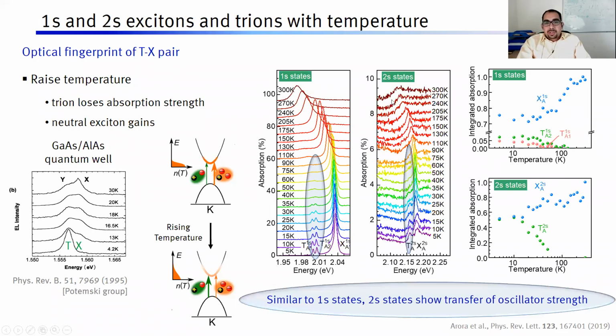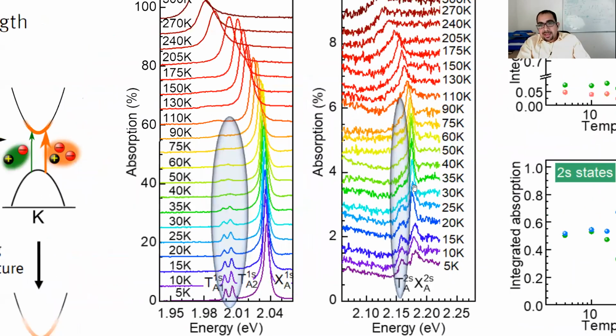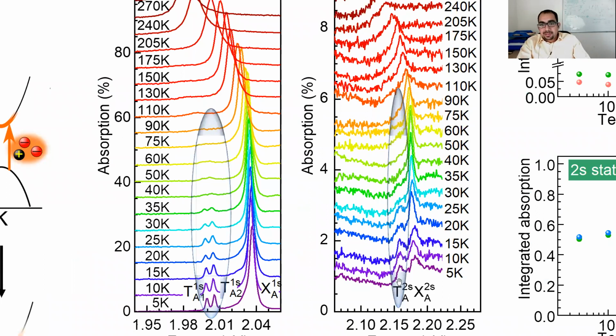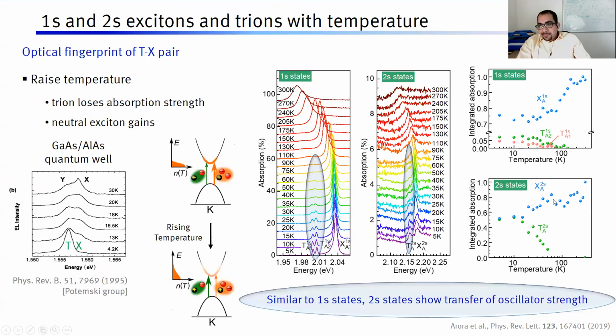Now let's go to the 2s states. We see a very similar thing. The 2s exciton rises in strength. I can even zoom into this. You can see that as I increase the temperature, it rises, whereas the Trion goes down in strength. So similar to the 1s state, it rises and it falls. That means the 2s states also show transfer of oscillator strength, which is another evidence that this has to be a connected exciton-Trion pair.